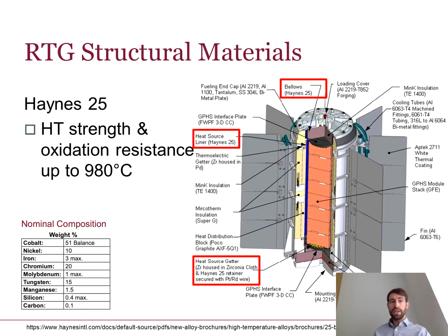And here we've got a combination of high temperature strength, so up to 980 degrees C. That is partly based off the high melting point of cobalt and nickel, and also the FCC crystal structure, which has quite slow diffusion kinetics. The other element of Haynes 25 is that it's got very high chromium content, and so this provides us oxidation resistance. So we have high temperature strength and oxidation resistance nearly to 1000 degrees C. You can see there are quite a few different points in the RTG where Haynes 25 and other nickel and cobalt alloys are used.